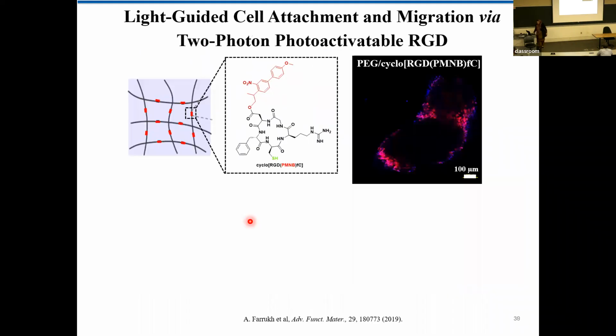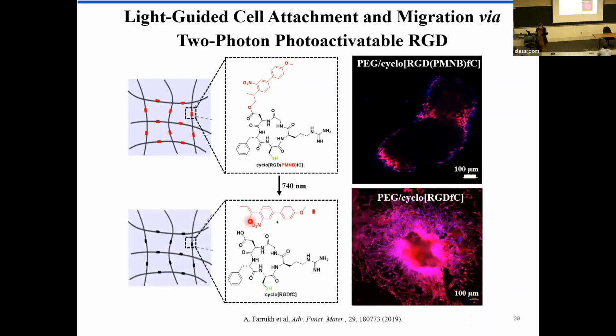Just to show the last part, in this case, we try to use a different caging peptide because we wanted to see how everything looks in 3D. Here we are using RGD peptide, which is also an extracellular matrix peptide. This peptide controls the migration of fibroblasts, basically. When we have the 3D gel with this caging group, the cells cannot grow. You can see that cells are dead. Every red spot is a cell. On the outer side, there are some cells which are still alive, but inside the gel, the cells are dead. This also tells you that if the cells do not get enough oxygen and enough supplies, they are going to die anyway. When we uncage it, when we have everything uncaged, there is no caging group. You can see the cells, they are migrating.